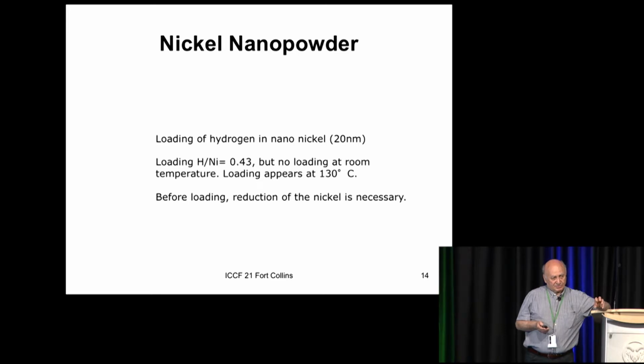Now, I've done some treatment. First, I remove the moisture, water, by heating in vacuum. Then I heat in hydrogen to remove the oxide layer, because there's always an oxide layer. People say it's dangerous. I didn't find it dangerous. I know some people had problems with it, but I'm immune to nickel, maybe. I'm part of the 90% because of my diet. I'm a vegetarian. That helps. I don't know which one is true, or both. Anyway, it's not like a powder that goes everywhere. It's very heavy, it stays. Even though it's nano, the grains are not nano. They are just sticking together, chunks of metal.